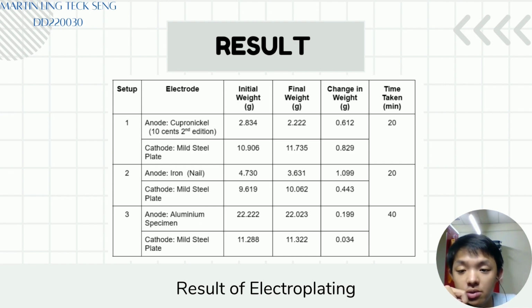From the table, we can find out that in 20 minutes, there are very obvious changes in the weight of setup 1 and 2, in which the weight of the copper-nickel anode decreased by 0.612 gram, and the weight of the mild steel plate cathode increased by 0.829 gram. And for setup 2, we can find that the iron anode decreased by 1.099 gram, and the mild steel plate cathode increased by 0.443 gram.